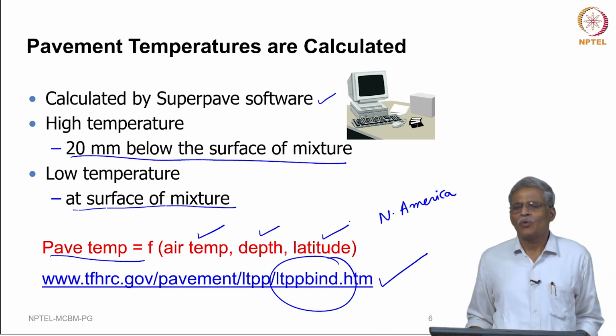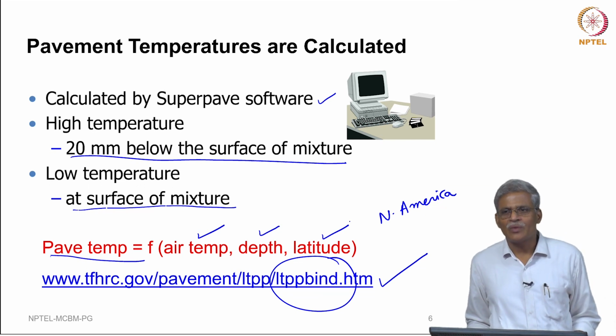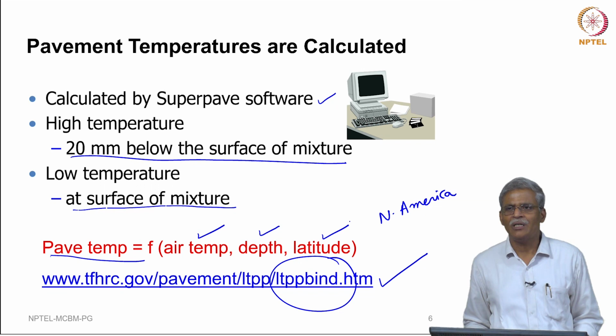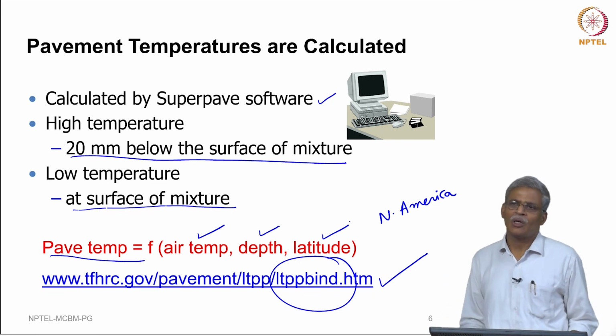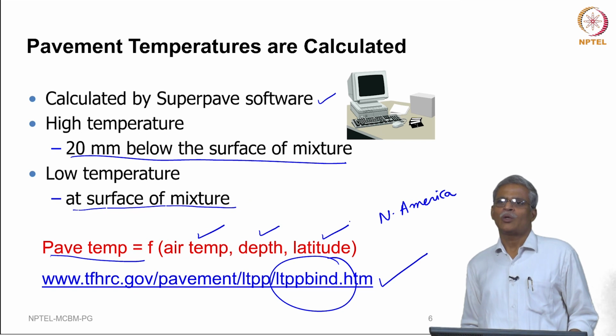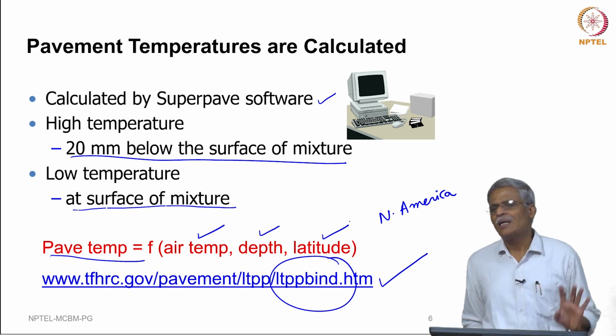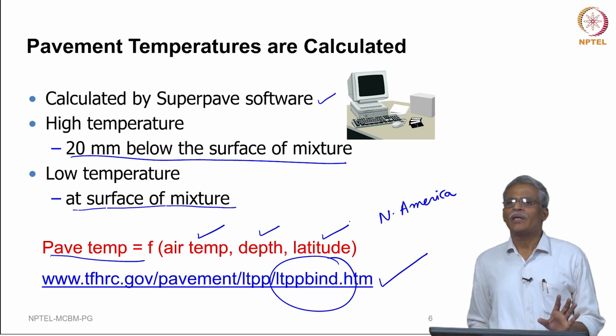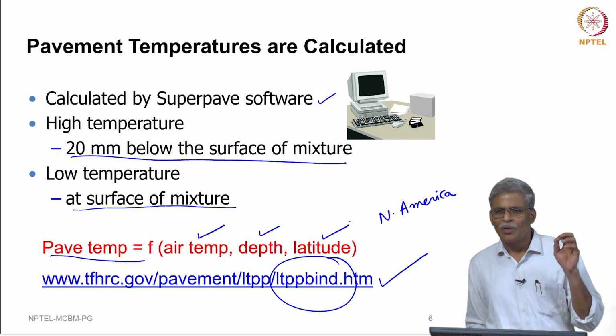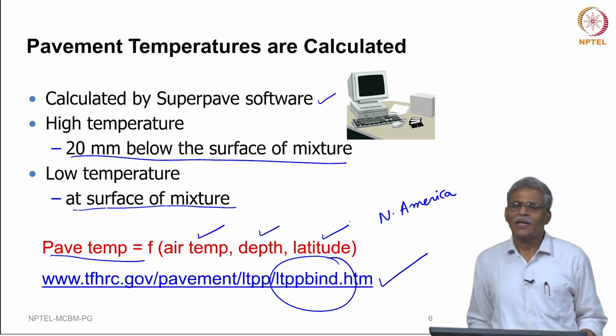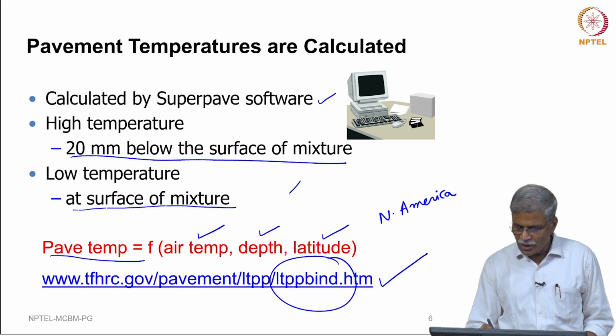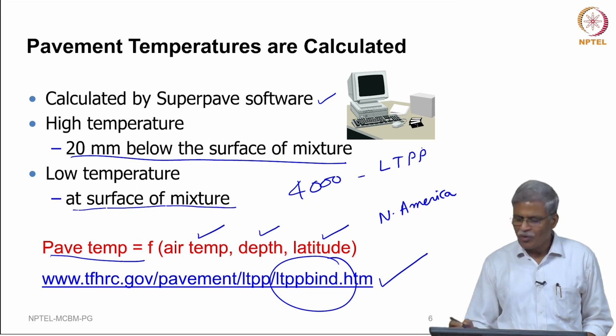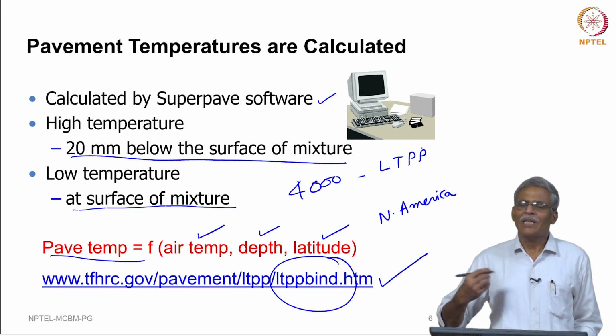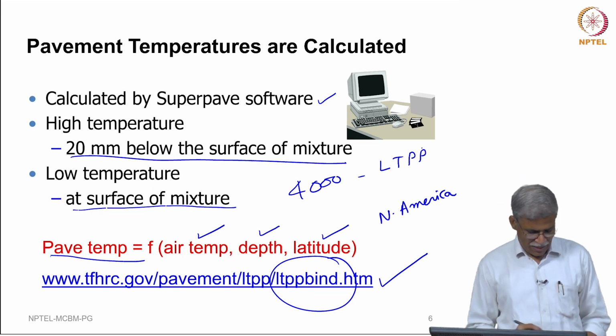And in fact, if you recollect the discussion that we had on viscosity graded bitumen specification, we showed you a chart of high temperature pavement as well as low temperature pavement for Indian conditions. It was based on a very limited amount of field data. If you really have to have a substantial amount of pavement temperature data, the kind of data that has been collected from more than 4000 locations as part of the Long Term Pavement Performance program in the US, that kind of data needs to be collected for India, right.